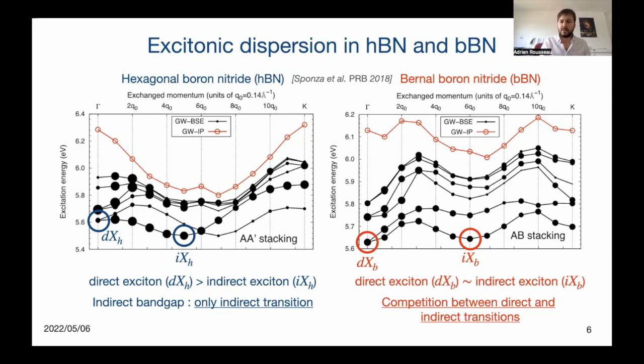The excitonic dispersion in hexagonal boron nitride shows a minimum, an indirect minimum, which corresponds to the indirect exciton, which lies 100 milli-electron-volt below the direct exciton, which explains the phonon-assisted indirect emission observed in hexagonal boron nitride.